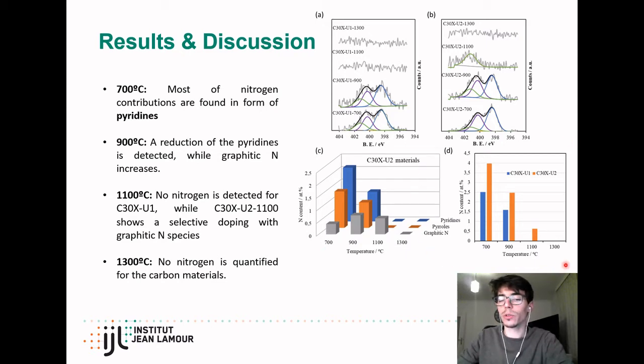Figure D, on the other hand, shows the total nitrogen content determined by the XPS. As we can see in here, the control over the carbon-urea ratio of the functionalization process enables an excellent control over the final functionalization degrees of the heat-treated sample, since the carbon-urea ratio of 1:2 always saw larger functionalization degrees than the homologous in a carbon-urea ratio of 1:1, which is especially important at 1100 degrees since the carbon-urea ratio of 1:1 doesn't show any nitrogen content, but while the carbon-urea ratio of 1:2 still shows a large contribution of nitrogen content, a large contribution of graphitic nitrogen functional group.